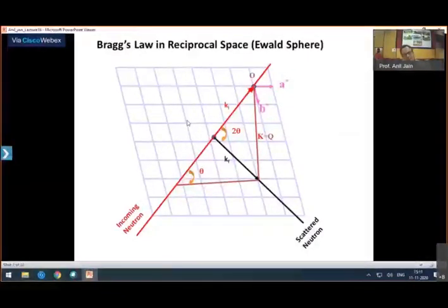So you have to rotate and tilt your sample to bring all these reciprocal lattice points, which may be above this horizontal scattering plane, into the horizontal scattering plane, so that you can carry out an omega scan on those and get the integrated intensity of each Bragg spot.